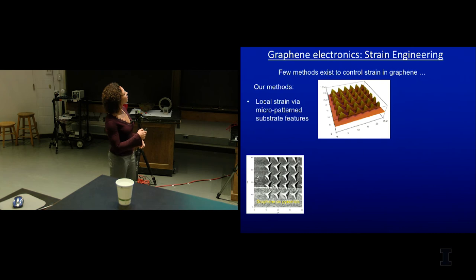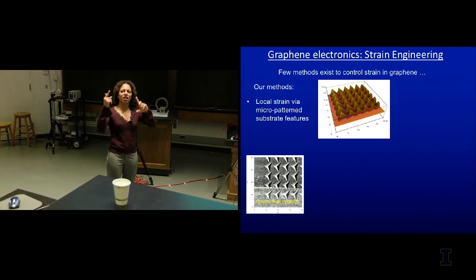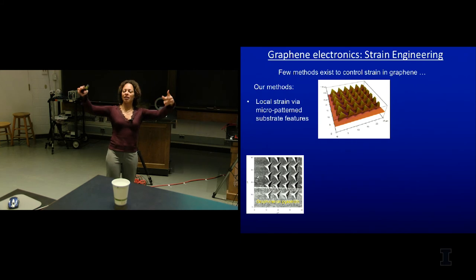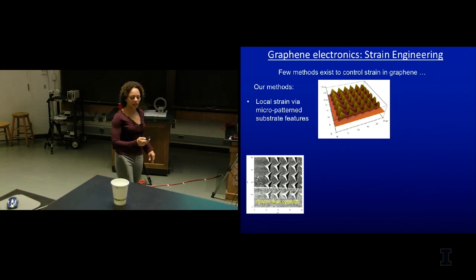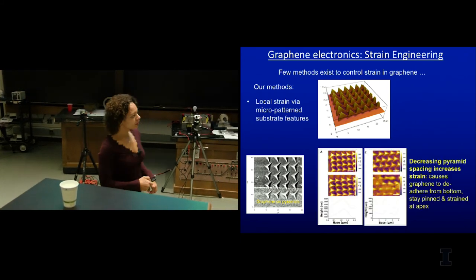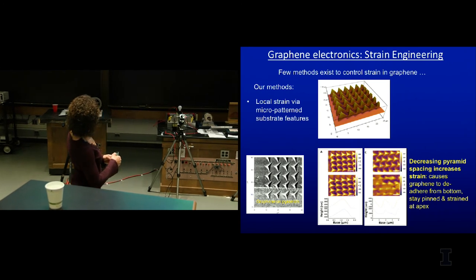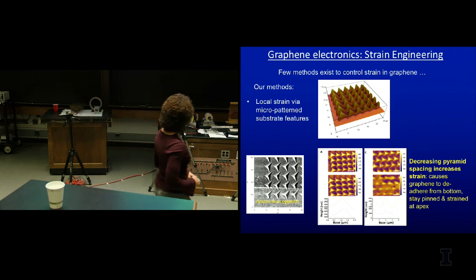Again, this is a 25 micron scale, so we made nano-patterns, put graphene on top, where we want to strain it locally. As the graphene drapes across, it bends in a controlled way. We can control its electronics that way. And we could see, if you look, these are images of what happens at the surface, and you could see that for far apart pyramids, the graphene just conforms to the surface, and as you get them closer together, it starts de-adhering because of strain, so you can control the strain that way.